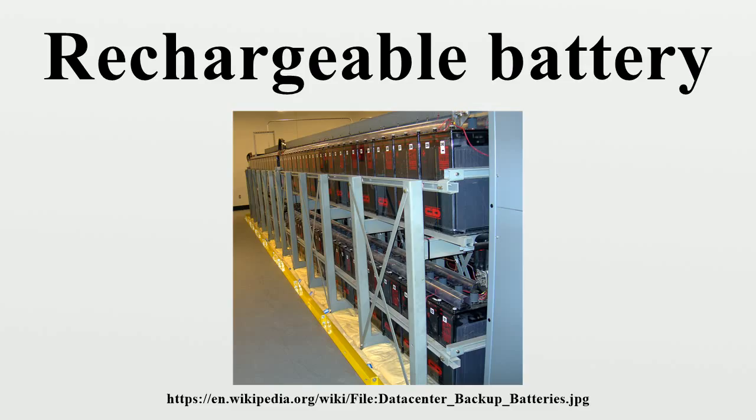Even if a cell is brought to a fully discharged state without reversal, however, damage may occur over time simply due to remaining in the discharged state. An example of this is the sulfation that occurs in lead-acid batteries that are left sitting on a shelf for long periods. For this reason, it is often recommended to charge a battery that is intended to remain in storage, and to maintain its charge level by periodically recharging it. Since damage may also occur if the battery is overcharged, the optimal level of charge during storage is typically around 30% to 70%.